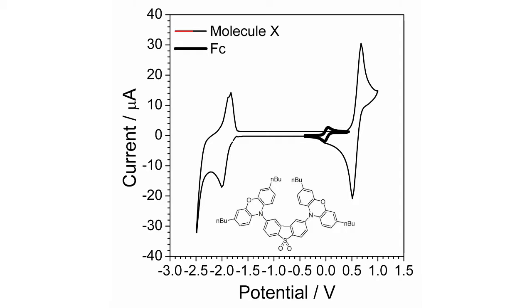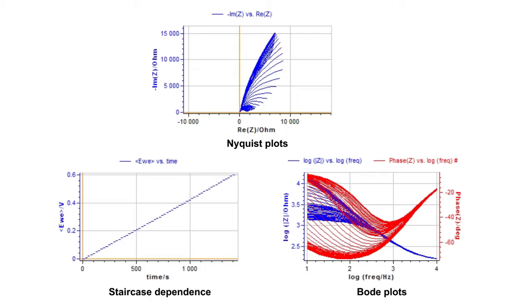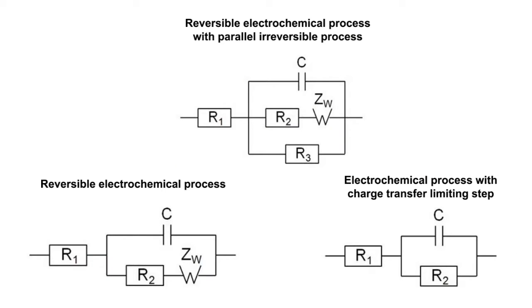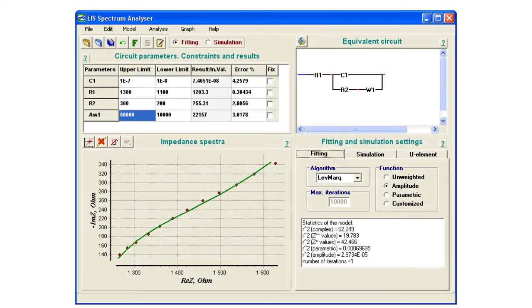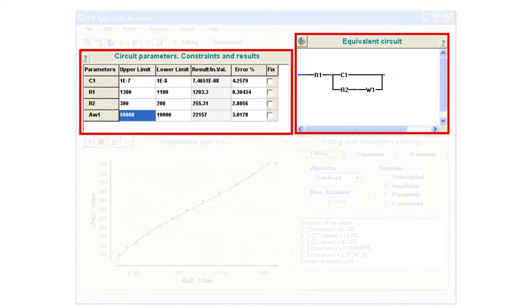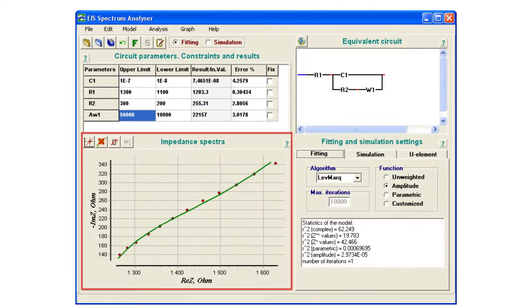Cyclic voltammetry of this organic compound revealed a reversible oxidation process at 0.7 volts versus ferrocene. Impedance spectra of the redox processes on the electrode surface were subsequently registered and analyzed. The impedance spectra were fitted with various equivalent electrical circuits to identify the best analog for the electrochemical process. The charge transfer resistance, represented here as R2, was extracted from each fitted spectrum.